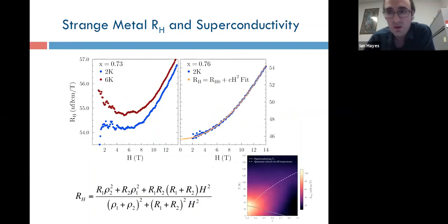And if you continue all the way to the overdoped, the very edge of the superconducting dome, at like 73% phosphorus substitution, this is a sample with an about 1 Kelvin TC, it's right on the edge. You see a very small, 2% or so decrease in RH at a few Kelvin. And then if you go to the next sample over, you don't see any decrease at all at 2 Kelvin. What you see is a pure H squared fit, which seems well described by simple multiband physics.